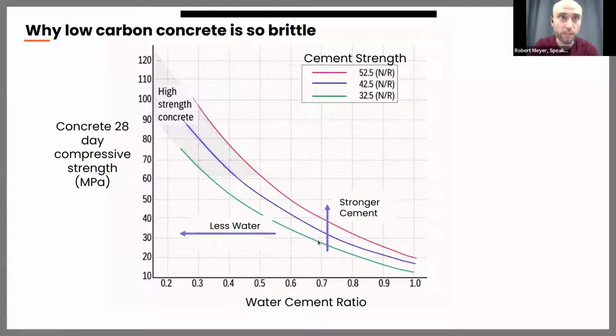my resulting concrete. But if I now actually cut the water in half, so I don't take 7 liters, but just 3.5 liters, but I leave everything the same, what will happen is I get much, much stronger concrete. So just by cutting the water in half, even with this weak cement, I end up with something like 60 megapascals. So that is a very fine lever to really increase the strength of my final building material. It's just reducing the amount of water.